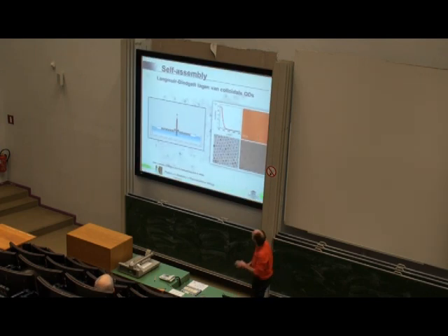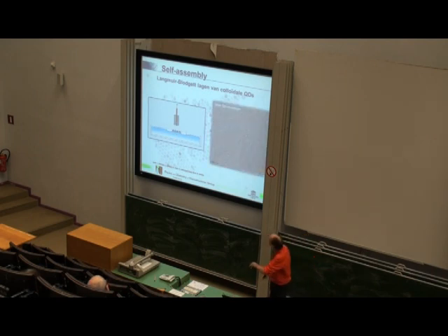Let's go to some physical chemistry. I will be very short in there. I just need it at the end of my talk. It's a way that we use to assemble these different nanocrystals into monolayers. And we use here Langmuir-Blodgett deposition. It just means we have a trough, the blue thing that you see, it's water. With their hydrophobic ligands, these particles will float on water, and you can make monolayers of that. And you can compress this film, and you can actually extract the substrate and transfer this film to a substrate.